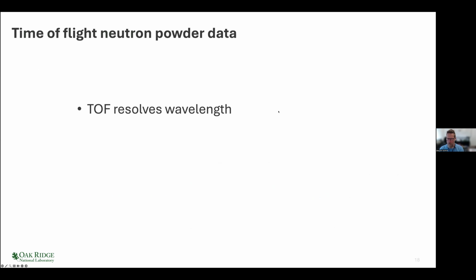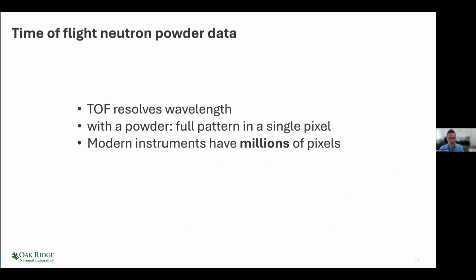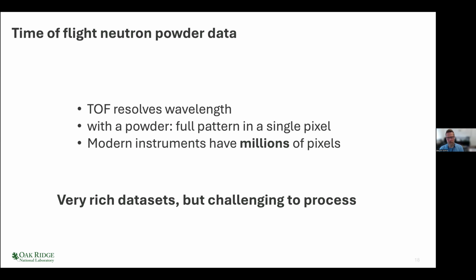So time of flight allows you to resolve wavelength, and that means if you have a powder, you get a full diffraction pattern in a single pixel. But actually, modern time of flight instruments have millions of pixels. So that is an extremely rich data set, but as a natural consequence of that, it can be challenging to process.